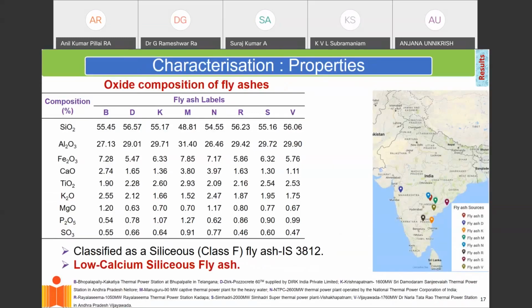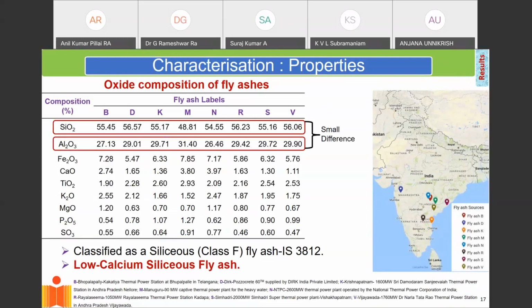So we started looking at fly ashes across India. We collected fly ashes from different thermal power plants, and they're labeled on the top, B, D, K. Those are the different power plants. And when we did the oxide analysis, we found that more or less the main oxides, the silica and the alumina present in the fly ash, are consistent. But when we started using them in cement, we found that the results were very different. So clearly, only the oxides, as indicated by oxide analysis, are not indicative of the reactivity of fly ash.